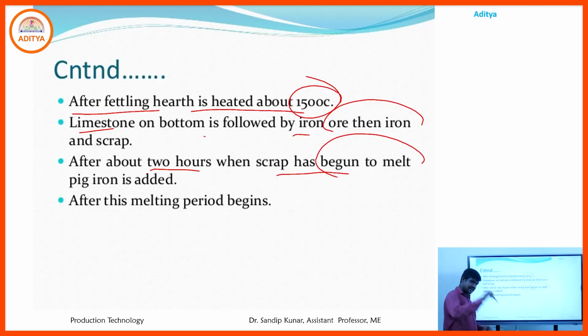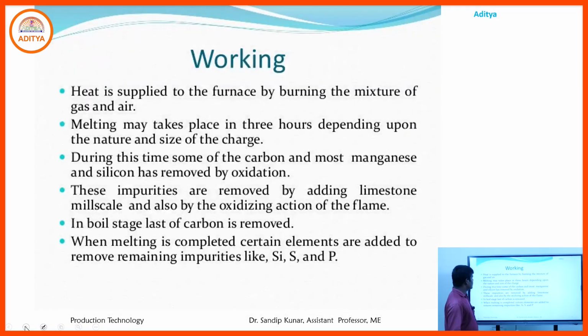Then we add the pig iron. After this, the melting period begins. After the scrap melts, the iron starts melting, when heat is supplied by the mixture of preheated gas and air. Melting takes place in about 3 hours, depending upon the size of the charge.